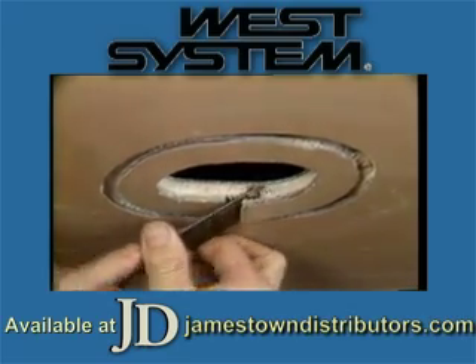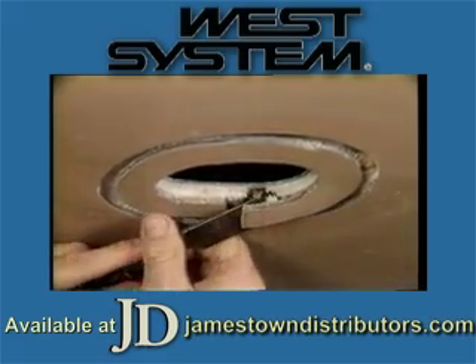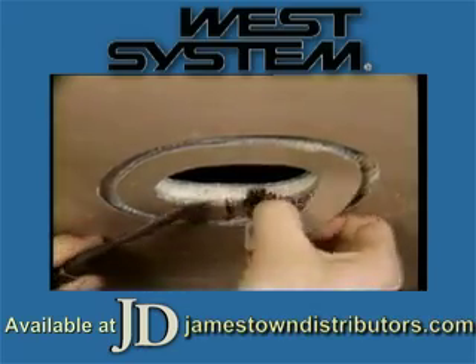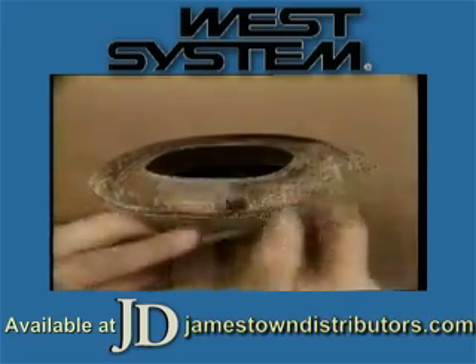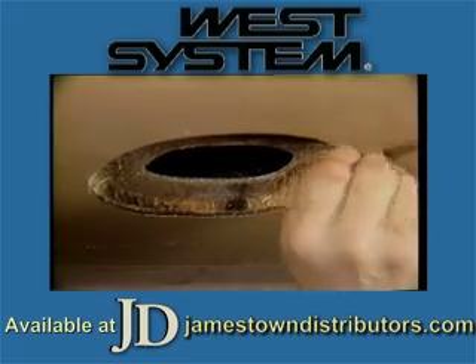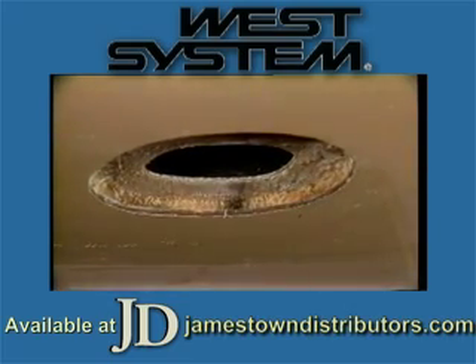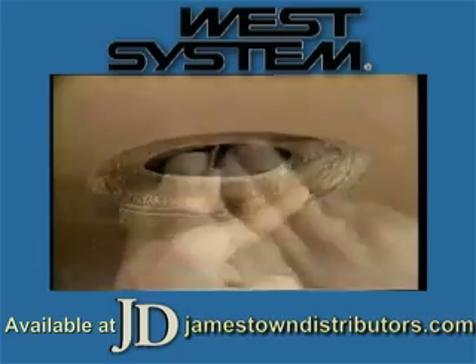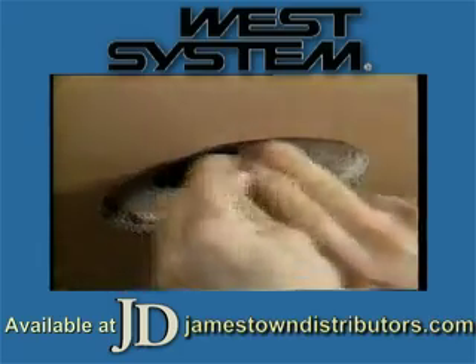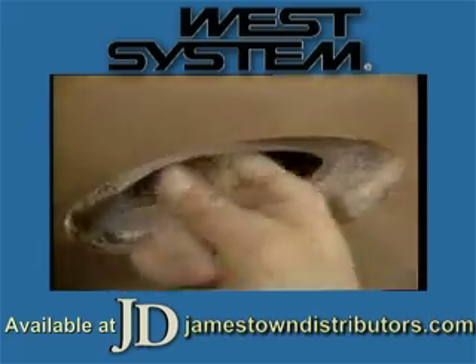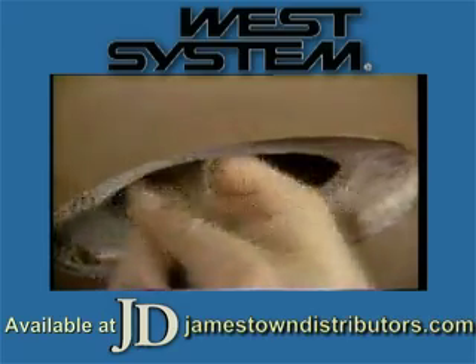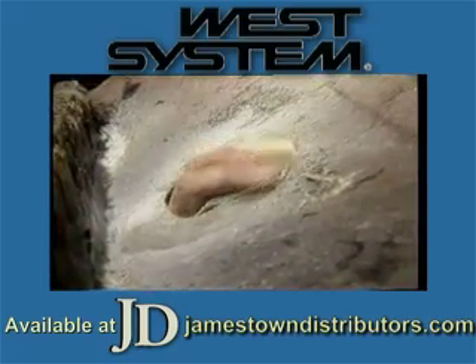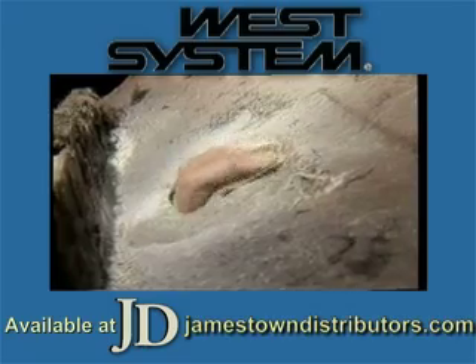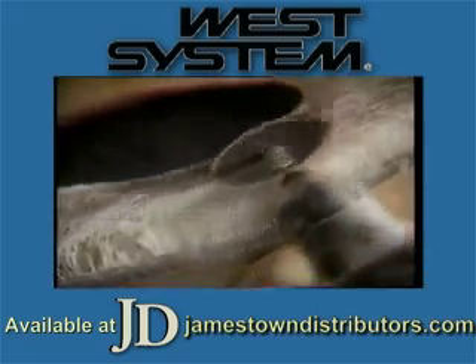Chisel out the skin and the core material. Be sure you've exposed sound core on all sides of the hole. If the core is damp, dry it with heat lamps or a hot air gun. Wipe the inner skin with solvent to remove any remaining adhesive or contaminants. Sand the skin and the exposed core material with 80 grit sandpaper, and sand the inner edge of the hole slightly to reduce stress concentrations.